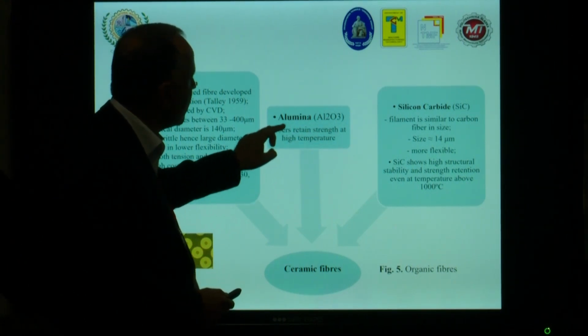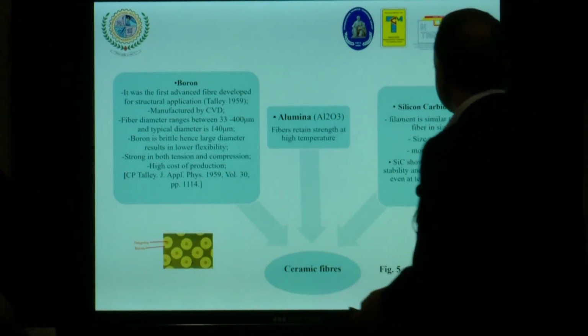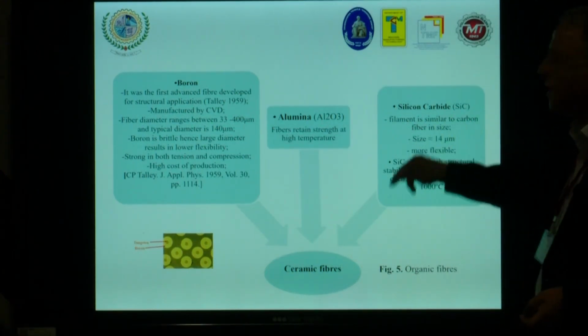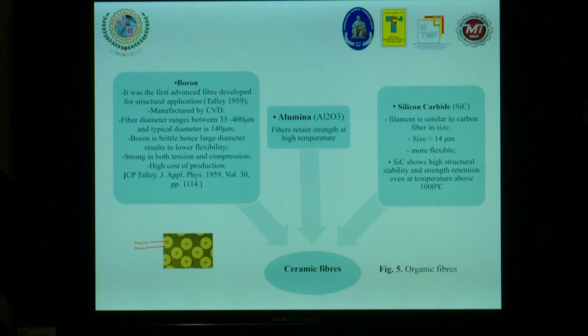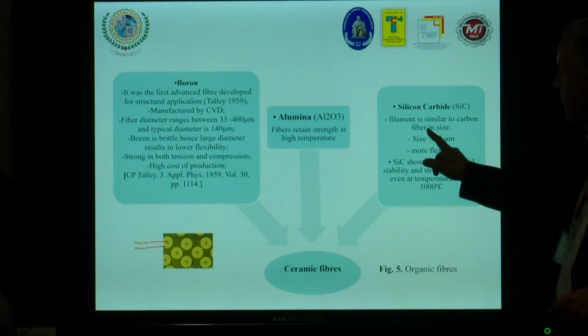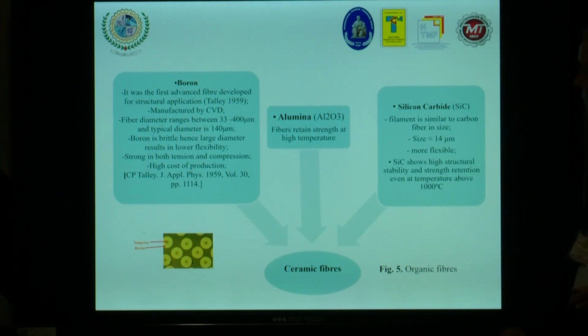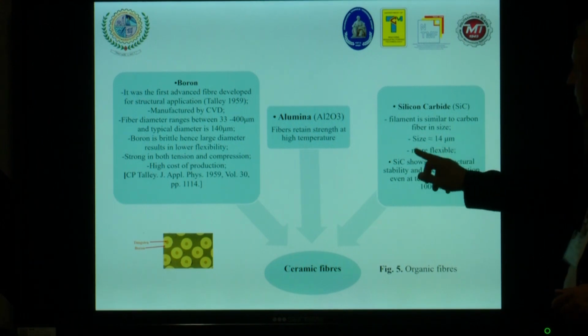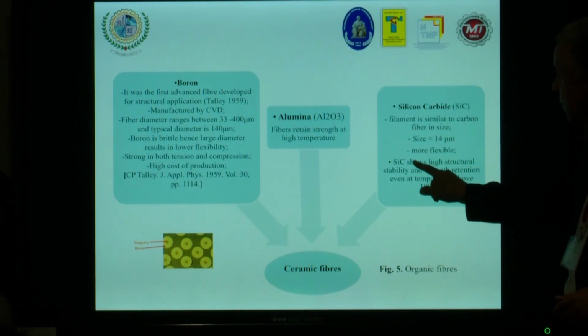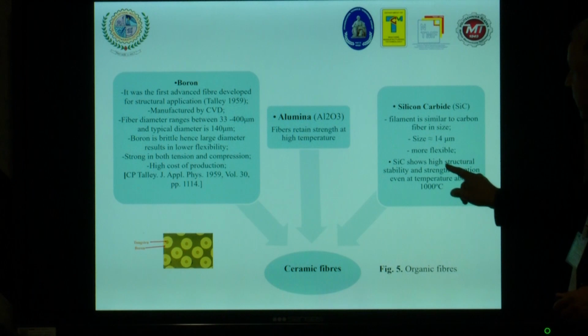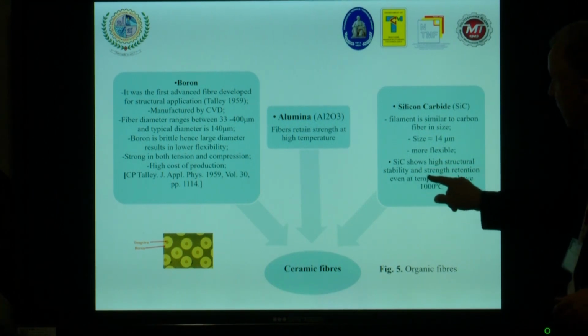Alumina fibers retain strength at high temperature, and silicon carbide, you can see the filament is similar to the carbon fiber. I mean, take into account the size, around 14 micrometers and more flexible. Silicon carbide shows high structural stability and strength retention even at temperatures above 1000 Celsius.